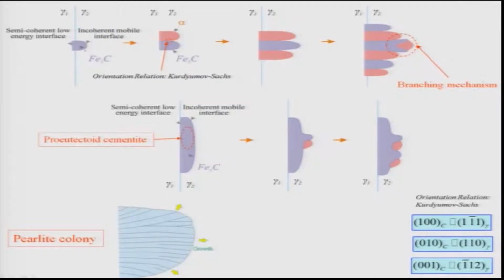So what will happen, as Fe3C is a carbon rich compound, it requires more carbon for its growth. When it grows into one of the grains with which it has an incoherent interface, that is obvious, because the grain with which you have a coherent interface will remain stagnant, because it will like to keep these coherent or semi-coherent interfaces present. It will not try to disturb them. That allows it to have low energy, and the grain with the incoherent interface will be the one which is mobile. So as this Fe3C grows into the gamma 2 grain, it requires carbon. All the carbon from the nearby region will diffuse into it. That is how it can achieve a sufficient amount of carbon for its growth. And because of carbon diffusion from these nearby regions in the gamma 2 grain, those regions will be lean in carbon concentration, because carbon is diffusing through the gamma and reaching these Fe3C nuclei to grow.